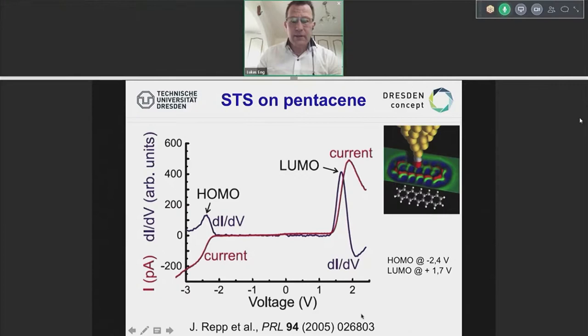And what they've done, actually, which is Jascha Repp here that you see, this is a reference. They took a very simple pentacene molecule, one, two, three, four, five rings of C6 molecules, and then did exactly, as you can see nicely, spectroscopy. Put the tip permanently on top and then measure an IV curve like shown before, which is the current here on the left, and the voltage on the bottom. Now, the current stays the same, close to zero, as you can see, and then goes up again. And that's exactly the values they find.